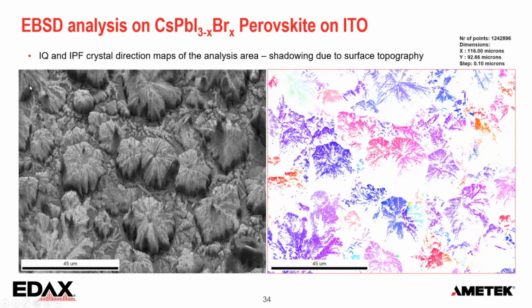Even this one, it looks a little bit skewed. So it's not straight up, but it's pointing sideways a little bit. Even there, we can get some information, it's a light greenish color. But from here, you can see that all those clusters are completely recrystallized and there's no trace of the original film that was deposited on the substrate anymore. So that was a really nice result.